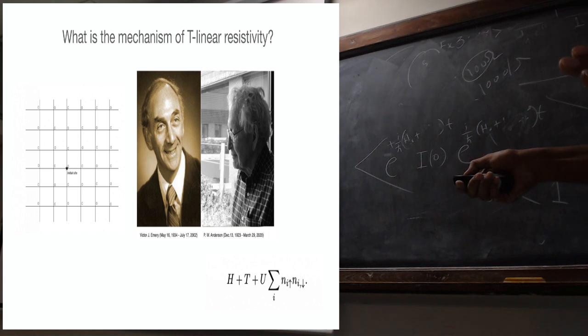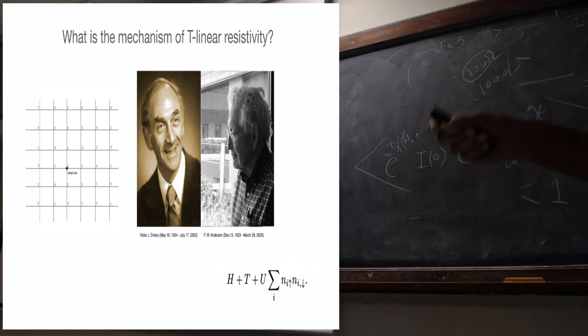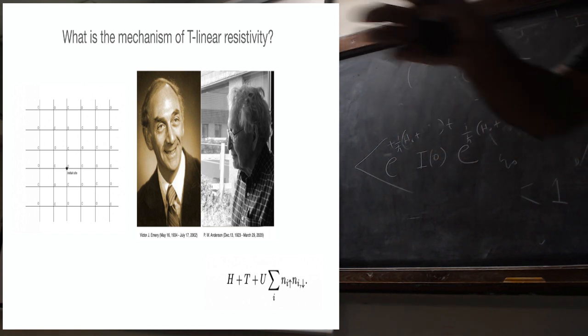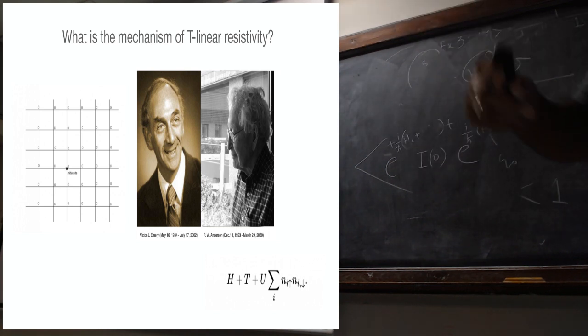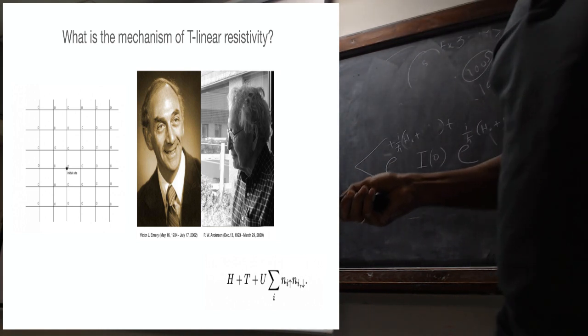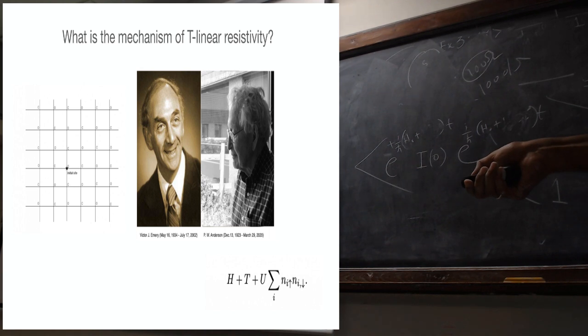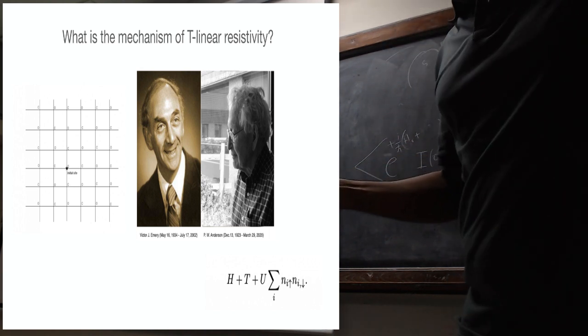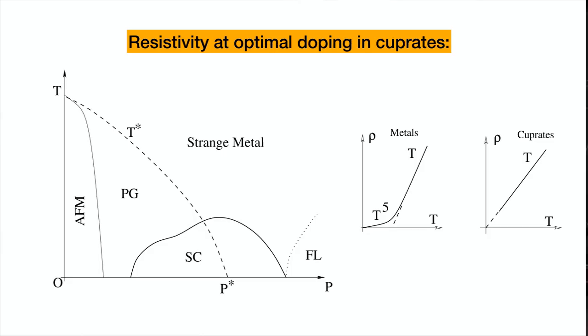So what we did is we took a simple two-band model, where the copper spins are a platform for paramagnons, and oxygen sites contain mobile electrons. Now the two components: the spins are pinned, in some sense. They are pinned because of Hubbard U. They are pinned on the copper, but they can fluctuate. Okay, with this model.